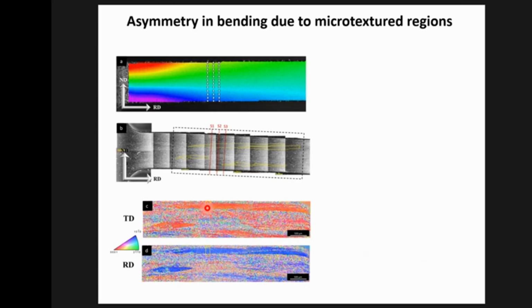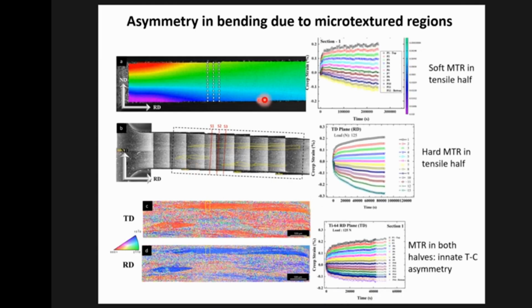So here are these microtextured regions. This shows you the orientation of the C-axis along the transverse direction. You'll see they are millimeters in length. These are extremely large inhomogeneities. So clearly, if they land up in either the top or the bottom half of the beam, it should be reflected in the way the beam deforms. And indeed, you can see that.